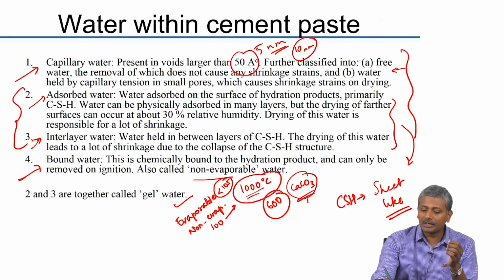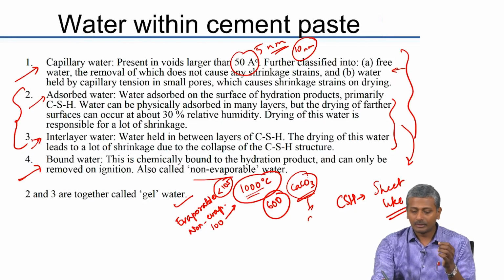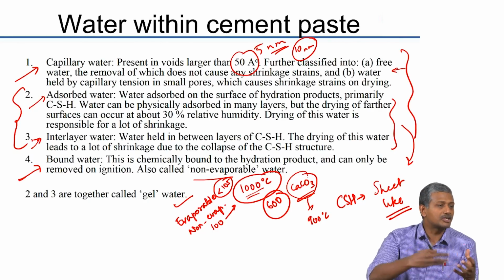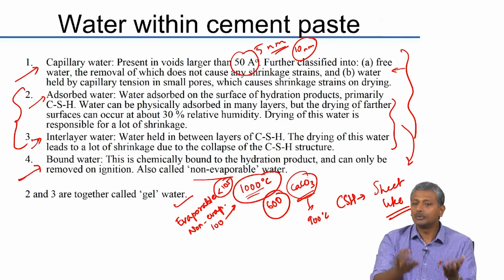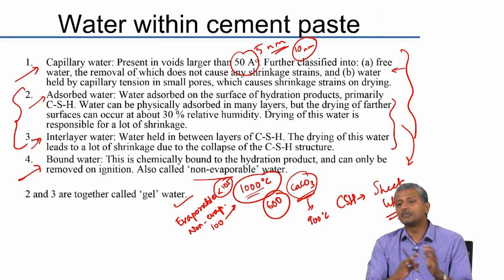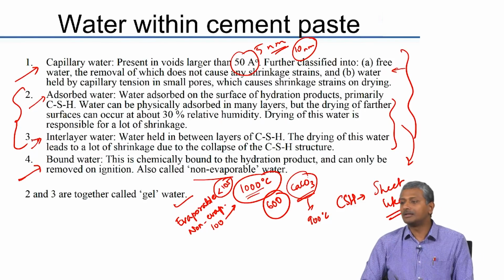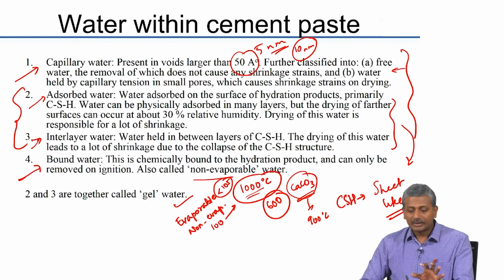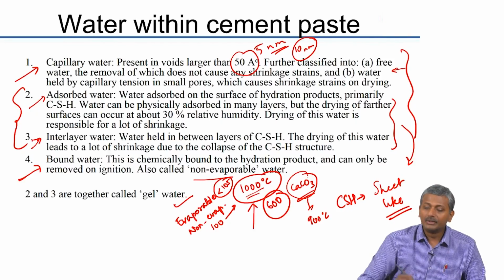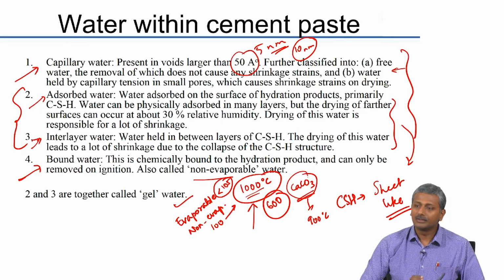So this calcium carbonate we saw earlier gets completely decomposed only at about 900 degrees Celsius. Remember we talked about this kiln reaction in which the limestone decomposes to release calcium oxide, that happens between 600 and 900 degrees Celsius. So depending on the purity and the form of the calcite that is actually forming, this carbon dioxide from calcite gets decarbonated at about 900 degrees Celsius. So that is why we actually go all the way up to 1000 to determine the extent of mass change that actually happens when cement paste is heated over a large temperature range.